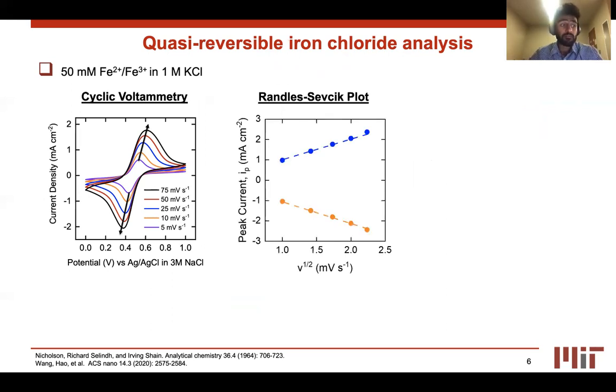Next, the Randles-Sevcik analysis was done where the peak currents were plotted against the square root of the scan rates. Here, scan rates in the range of 5 to 75 millivolt per second were plotted in order to determine the oxidative and reductive diffusion coefficients. From the equation below, the diffusion coefficients can be calculated from the slope of the linear fit.